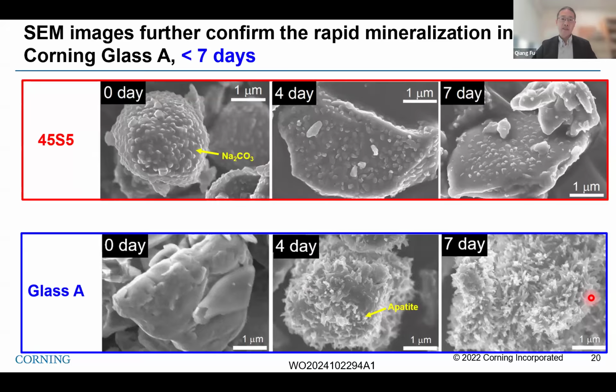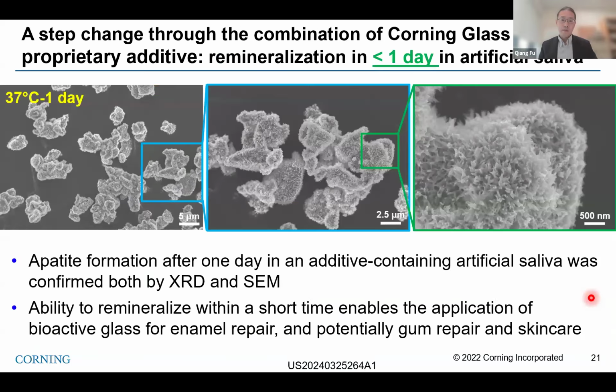So we did even further work. We put an additive in artificial saliva. What we found is we can actually form apatite within 1 day. So instead of 7 days without any additive, within 1 day you can see all these particles are covered with apatite. This kind of rough surface on the glass particle shows the formation of apatite.